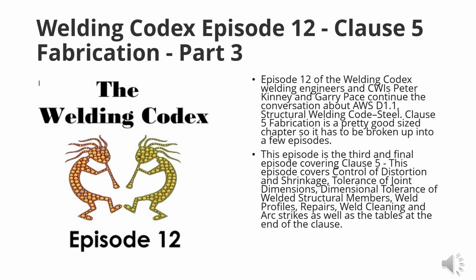Good catch there, Gary. Yeah, and then we've got cracks in weld or base metals. The extent of the crack shall be ascertained by the use of acid etching, MT, or other equally positive means. The crack and the sound metal to 2 inches beyond the end of the crack shall be removed and re-welded. So that tells you how to chase cracks in the weld or the base metal. So you can't just go to the end of the crack and call it good. You got to chew out a significant amount of material after the end of the crack.